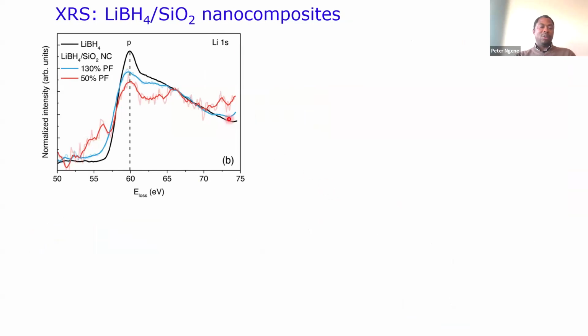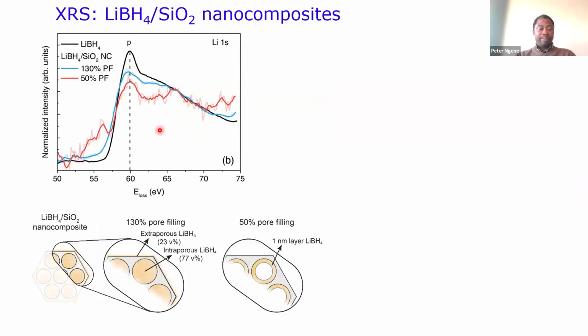So I start from the lithium 1s edge here. What did we do? We made composites that contain different amounts of the active material, which is LiBH4 in this case. So this is 130%. In this case, we fill all the pores and we have extra lithium borohydride outside the pores to really give us interconnectivity, and then we have an electrolyte that works. However, if you want to understand what happened at the interface, we have to make nanocomposites where we don't fill all the pores, so that we can probe most of the interface composition.